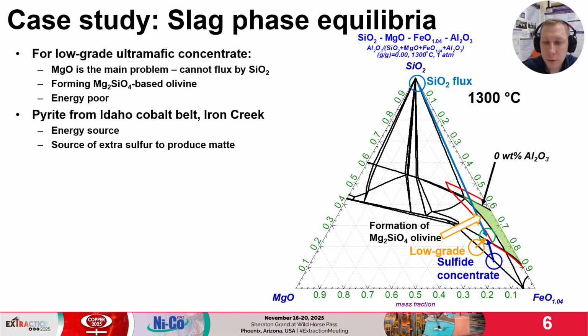Now, if we introduce low-grade concentrate, we will have too much of crystalline olivine in the slag. It is not possible to flux it by silica alone, but there is a pyrite source which together with silica can shift the overall slag chemistry towards lower MgO. Pyrite here acts not only as a source of energy and sulfur, but also as a fluxing for low-grade concentrate.